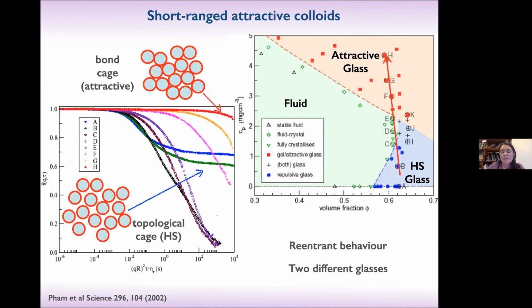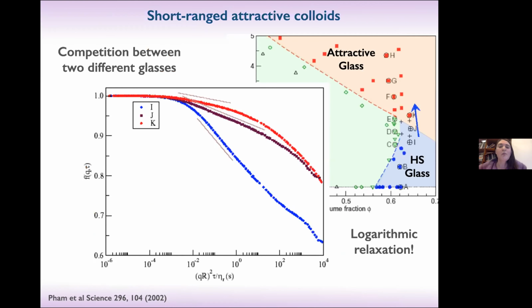One that is driven by the topological cage, the one we talked about before, and one that is stabilized by the bonds, by the attraction. You put a lot of polymer, the particles stick more and more together, and let's say more similar to a dense, very, very dense gel. And interestingly, there was this reentrant behavior and the occurrence of these two different glasses. But the one I want to focus on today is that if you then do the experiment here, more or less, and you try to go across this glass-glass transition, the dependence of the density correlator would be logarithmic, as the schematic models of MCT would have predicted.